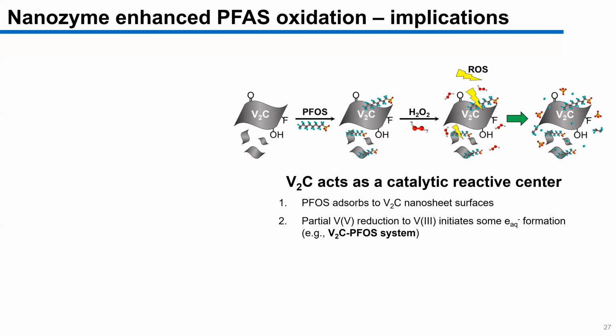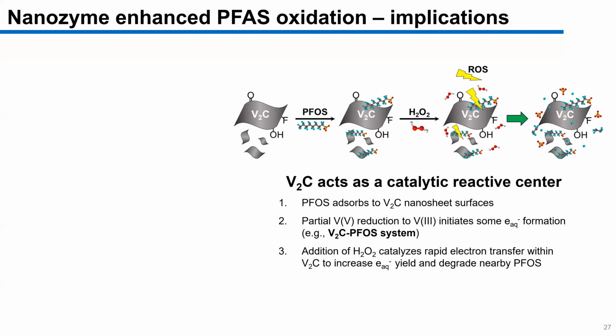But to really catalyze this reaction, you add hydrogen peroxide, and that promotes rapid electron charge transfer kinetics that are able to increase the yield of solvated electron species and degrade the PFAS that's adsorbed nearby. So again, we think the solvated electrons are attacking first, and then the singlet oxygen and hydroxyl radicals that are also forming can more easily attack the byproducts that are formed after that initial solvated electron. And all of that is what is contributing to complete PFAS degradation in our study.